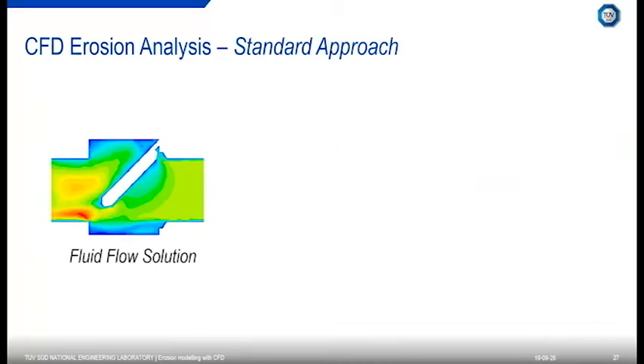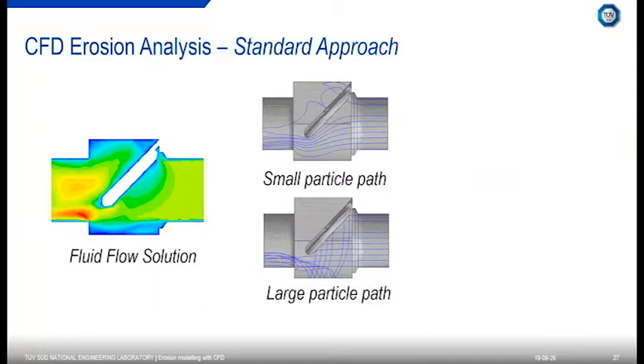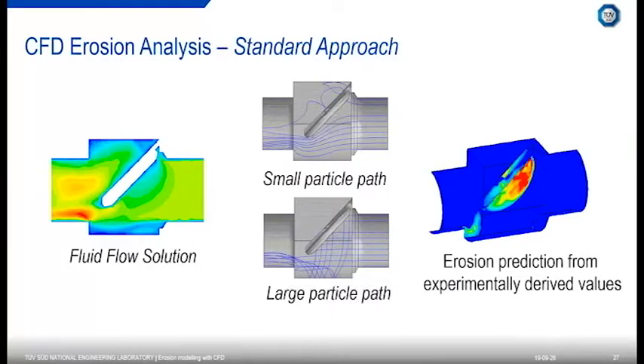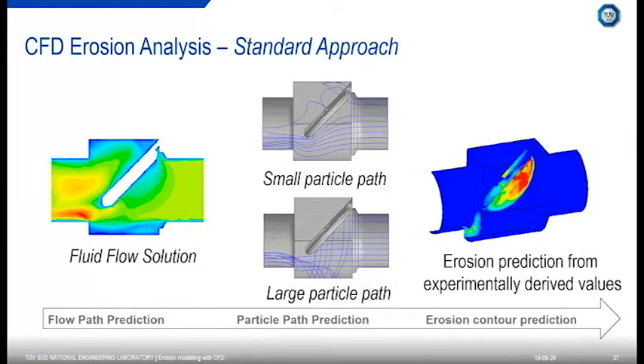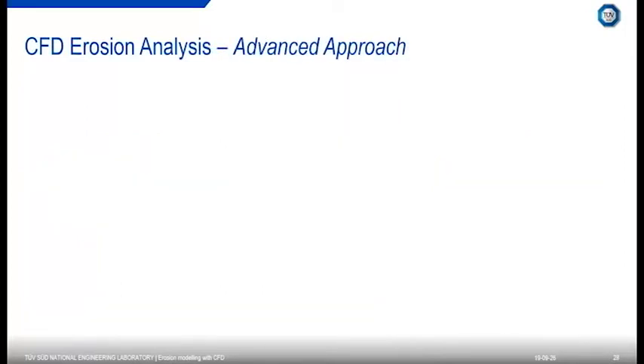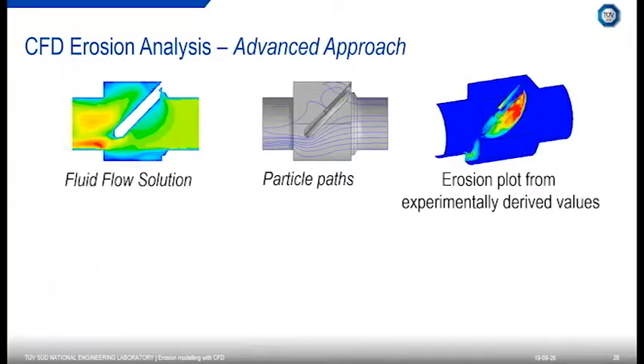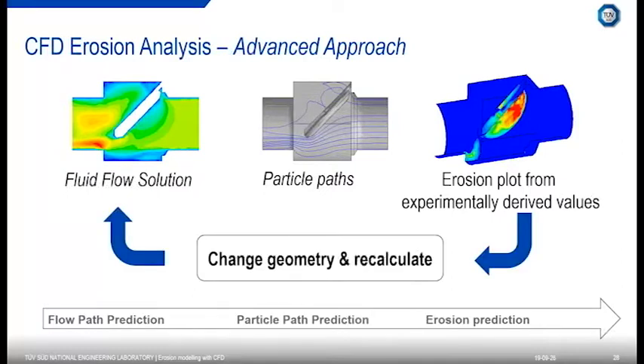So CFD erosion modeling. As I've explained, we have our fluid flow solution. We inject our particles, and this can be a different particle size distribution. Some will impact the wall, some will follow the flow, and we get our erosion prediction from experimentally derived values. And this is typically our standard approach. We also have a little bit more of an advanced approach, and this is important for flow meters, especially differential pressure flow meters. We have our fluid flow solution, our particle path, and our erosion plot derived from experimental values. What we can then do, one more step, is change the geometry based on these erosion rates and recalculate this.